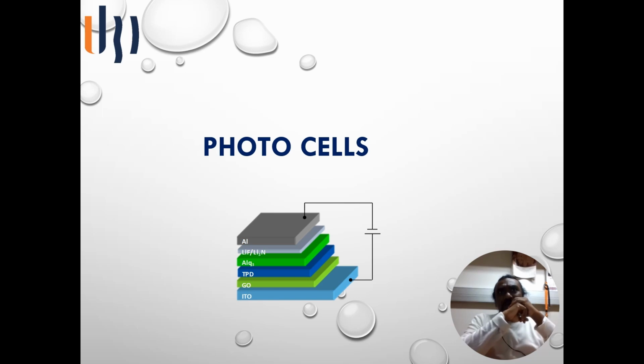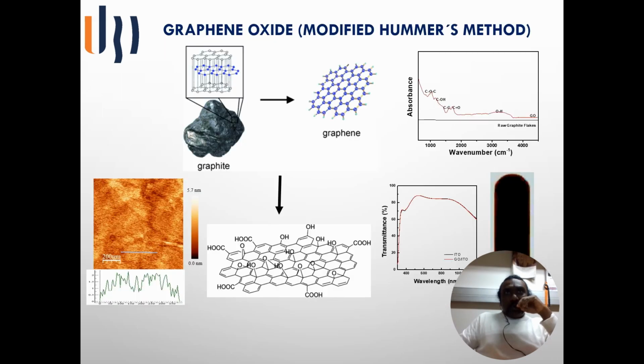When it comes to our academic research, we have developed a graphene oxide layer as a hole injection layer in organic LEDs. Here we have prepared graphene oxide out of graphite rocks. We used graphite and a modified Hummers method in order to oxidize graphite and give graphene oxide. This graphene oxide has multiple functional groups like hydroxyl groups and COOH groups, and these groups make graphene more solution processable for different applications, where you can deposit the graphene oxide layer on different substrates.